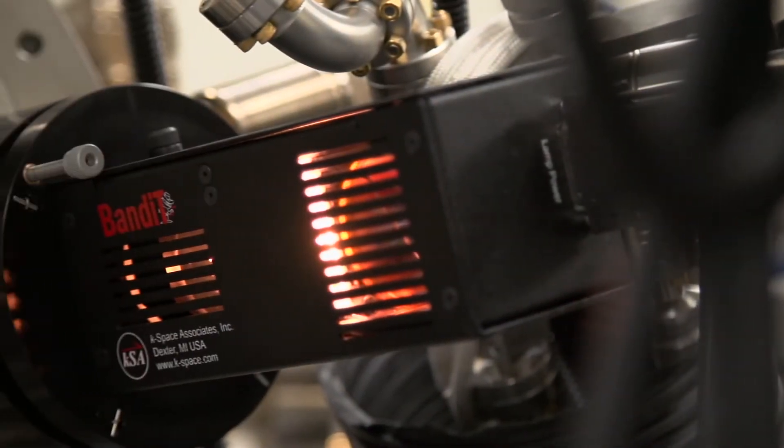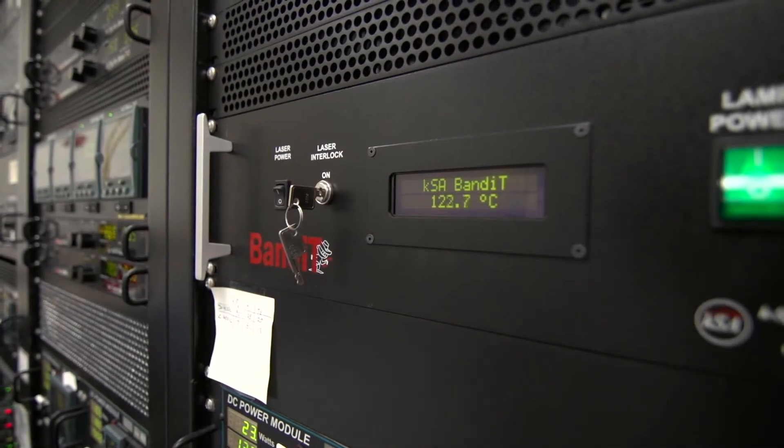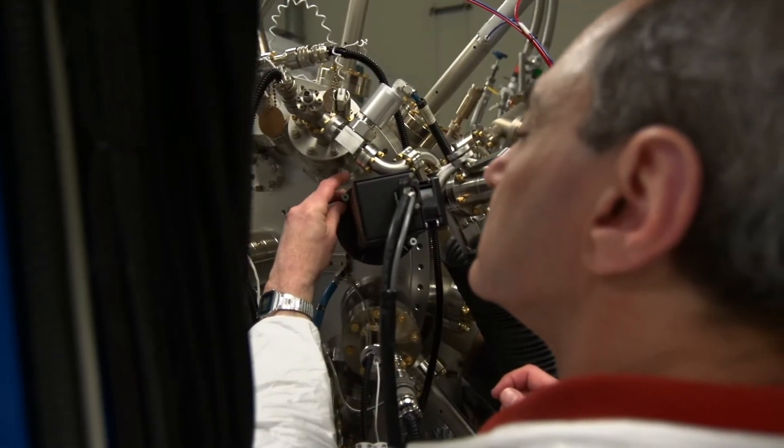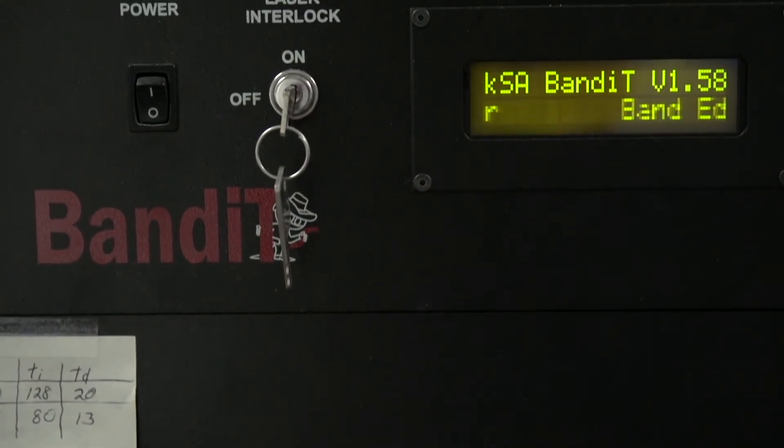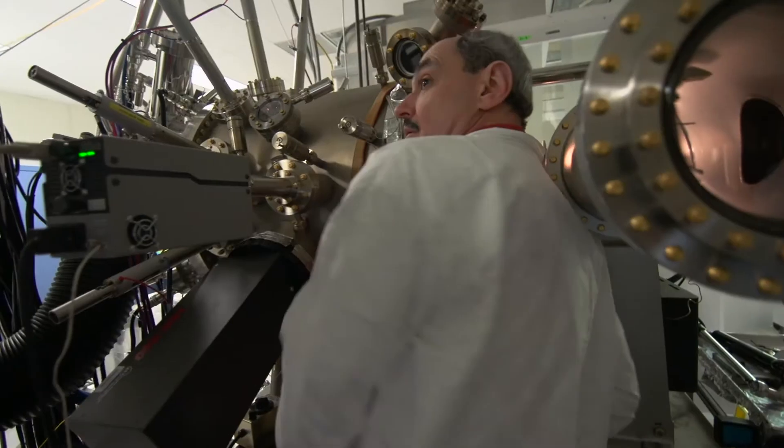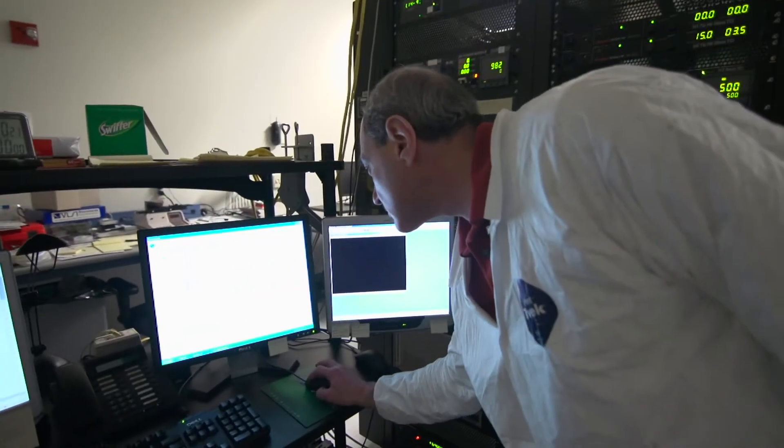Maintaining the control of those low temperatures to within plus or minus ten degrees roughly is absolutely critical to getting reproducible material quality. You can really fine tune the quality of the end device that you want to grow.